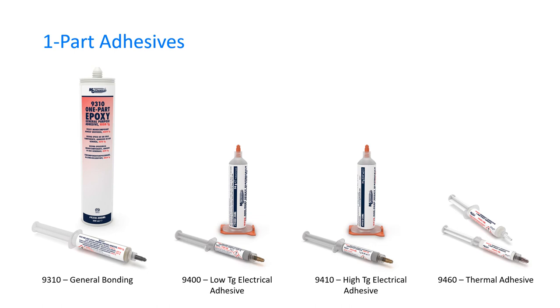Okay. 9410, though, because it is a higher Tg, also requires a higher minimum cure. And I want to say that's 90 degrees Celsius for that particular compound. Also, the 9410 is one of the softer one parts. So, when I talked about stenciling with the electrically conductive adhesive, the 9410, a lot of people will use that for stenciling. It's got a very soft, almost toothpaste type of consistency. So it spreads out and it's very easy to stencil on. And then finally, we have a fairly new product, the 9460, and this is a thermally conductive one part adhesive. So it's available in a 3 and 10 mL syringe.